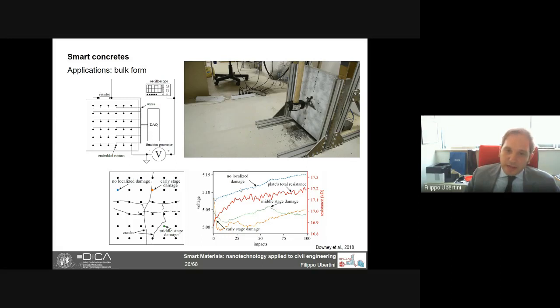And in fact, this electrode is located close to a middle stage damage. The blue line is referring to a location where we do not have any localized damage, and here we have a nice increase in resistance with increasing number of impacts. So what we can say from here, we have some change in the conductivity of the material due to the damage that we somehow can measure.